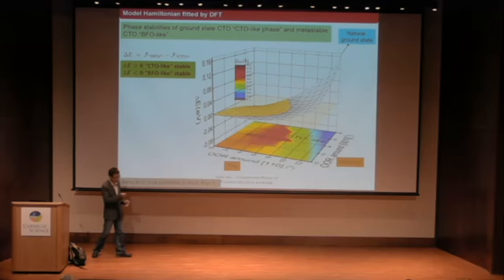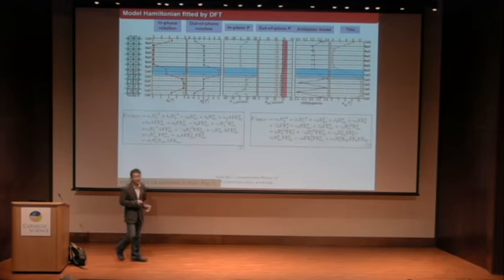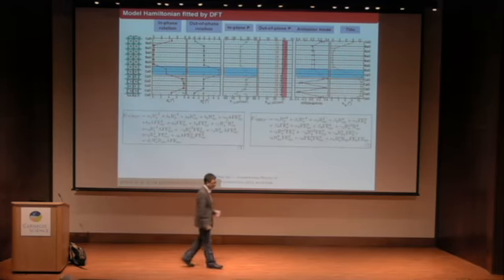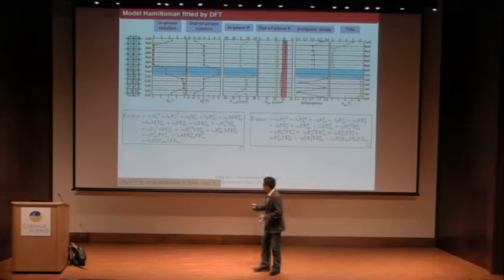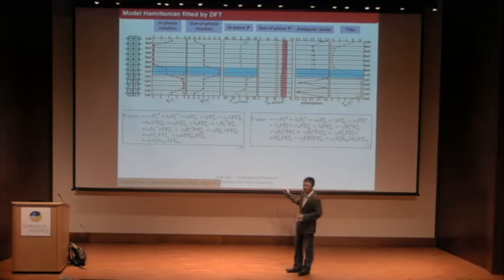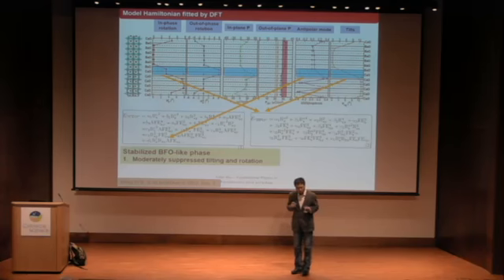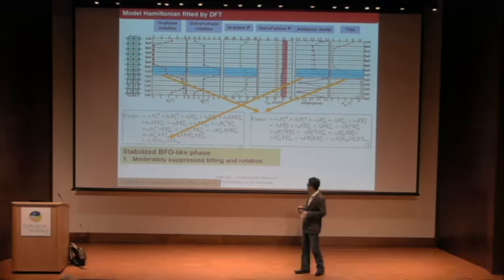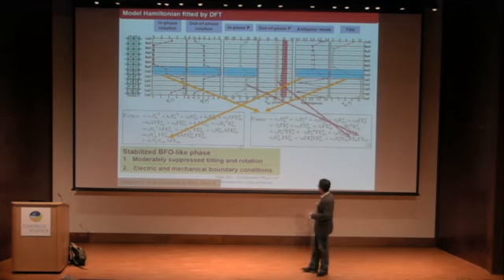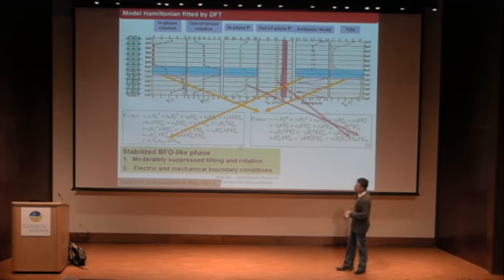So this tells you that we can understand our previously observed problem: the suppressed rotation and tilt at the interface help stabilize the BFO phase. And again, it's not only that, because the term in the BFO phase has a trilinear coupling - the ferroelectricity in the z direction and the ferroelectricity in the xy direction also help.